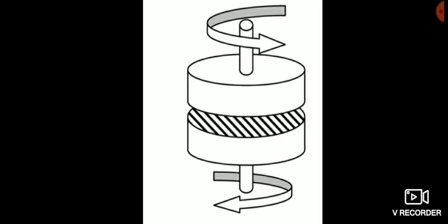The next one is disc grinder. In the case of disc grinder, these are suited for processing hard brittle materials. Wet grinding in a closed grinding vessel driven horizontally and eccentrically and which contains grinding elements is used to reduce the material to give a final particle size of a few micrometers. The impact and friction between the grinding elements and the grinding vessel cause such grinding energy that the process is generally concluded in a few minutes.